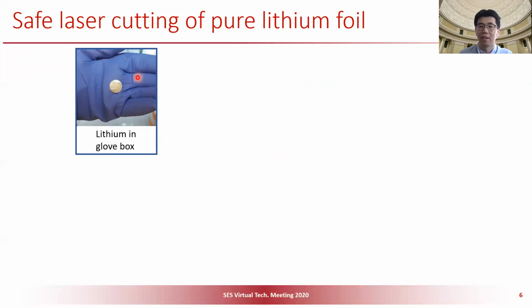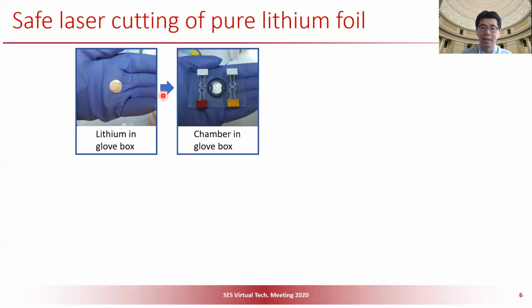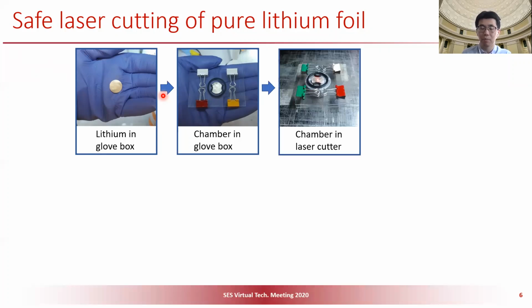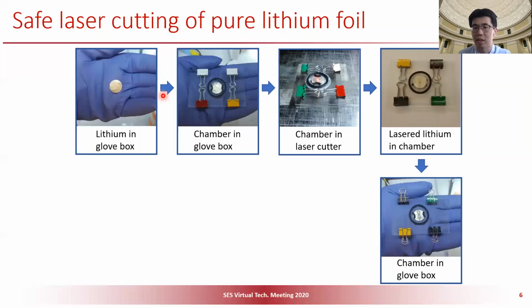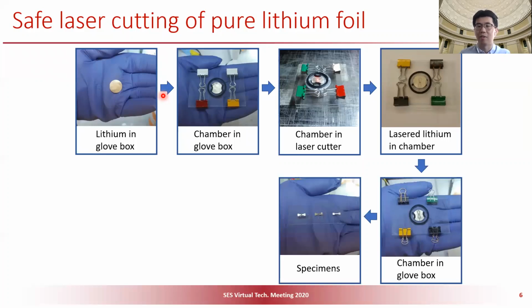Here, we cut the lithium disc in a glove box, and then we designed a small chamber, and it can be assembled in the glove box, and we stored lithium foil in this chamber. Later, we take this to the laser cutter. This device is designed to be transparent to the laser, so the laser can cut the sample while the sample is still in the chamber. These are the samples after we cut them and after disassembly.